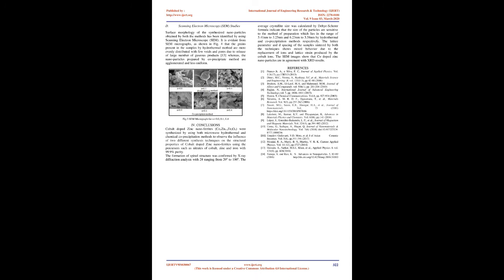C. Variation of d-spacing with the composition. The variation of the cobalt content with the interplanar distance, d-spacing, is mentioned in Table 1. It is clear from the data that first d-spacing increases from x equals 0 to x equals 0.1 and then decreases by further increase in Co concentration, both by hydrothermal and co-precipitate methods, which is attributed to the lattice strain produced by the cobalt ions.